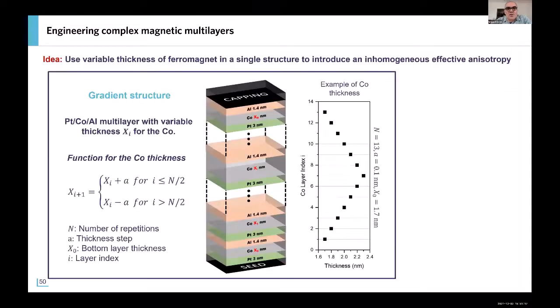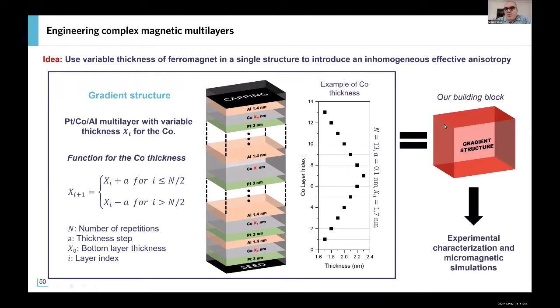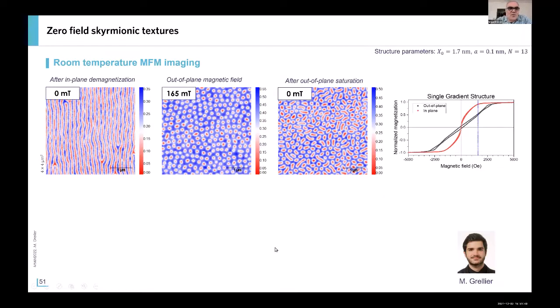So for that, we use multilayers, but this time where we vary one parameter. We started with a simple one: we vary the thickness of the magnetic layer along the Z direction of the multilayer. You see, we have here a variation of the cobalt thickness, and this is what we call the gradient structure. This work is the PhD work of Mathieu Grelier in our lab, that started about one year ago. So we can prepare a block, what we call a gradient structure, and look at the magnetic configuration. Again, we use MFM.